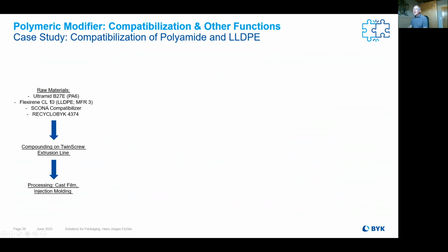What that means in a mixture of a polyamide and polyethylene, I will show in a few minutes. So we have done some work with a standard polyamide 6 grade and an LLDPE. We used our SCONA compatibilizer and we used our Recyclobyk grade. And we did a compounding on a twin screw extruder. And with these granules, we went over to our cast film line and did some injection molding.